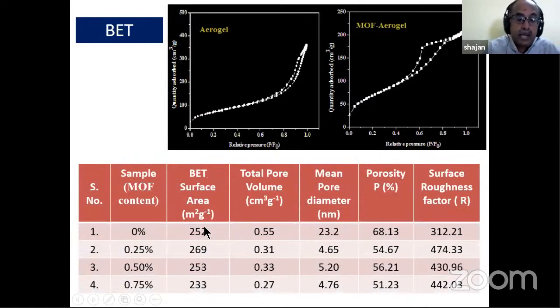This is a type 4 isotherm in the BET surface analysis. And you can see the surface area. For aerogel, it is 252 meters squared per gram. When we add 0.25% of MOF, it is 269, but then it keeps reducing. It is reducing below the pure one.